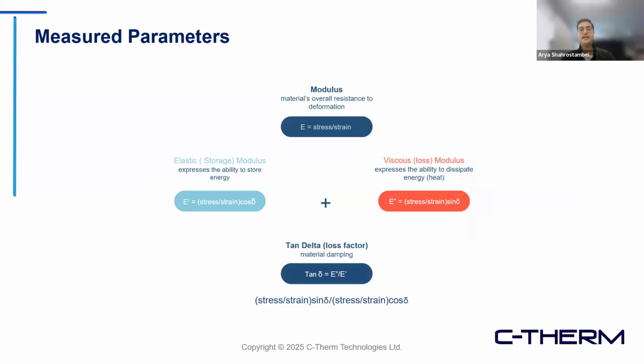Okay, but what can we obtain from a DMA test? There are many different parameters that you can benefit from a DMA test, but the key parameters that are very useful for different applications are modulus, which is basically the material's overall resistance to deformation, or in other words, the ratio of stress to strain. And this parameter has two components, viscous or loss modulus, which expresses the ability of material to dissipate energy through heat. And the other component is elastic or storage modulus, which expresses the ability of material to store that energy.